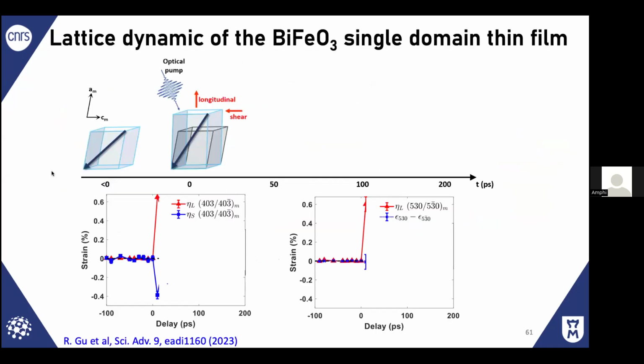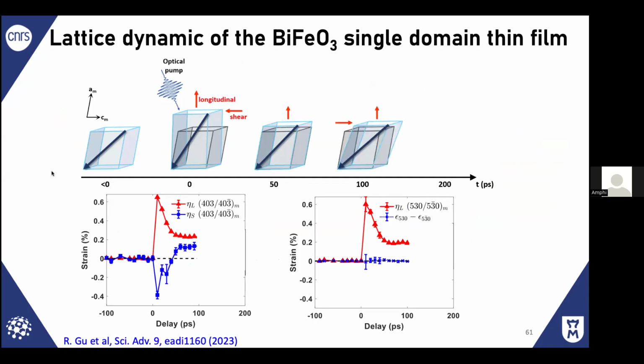When you shine light, there is first expansion, and there is a shear. After a given time, it's not relaxation, it's just propagation of longitudinal strain. And the shear is partially reflected and transmitted to the surface. And then step by step, you can reconstruct how the unit cell evolves as a function of time, thanks to the measurement of two Bragg peaks.